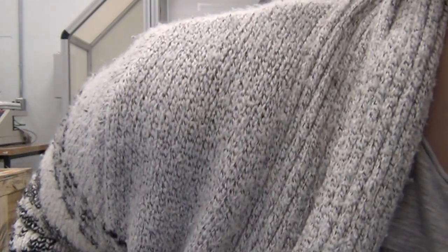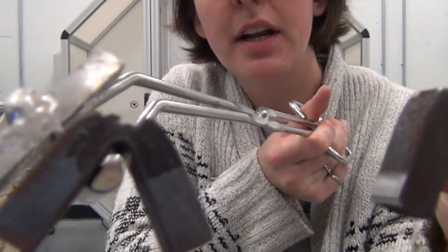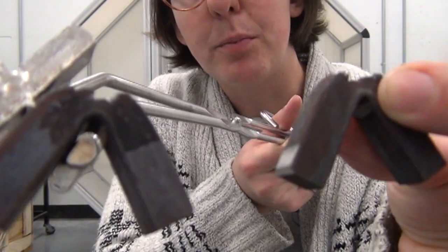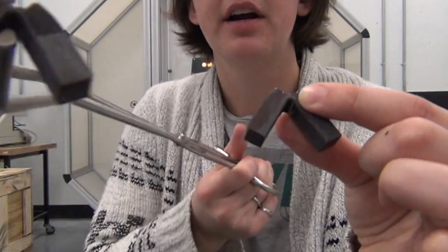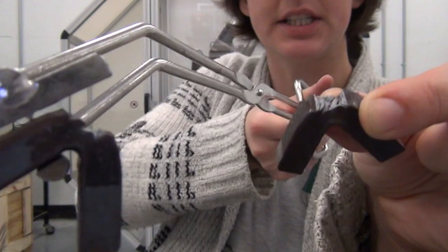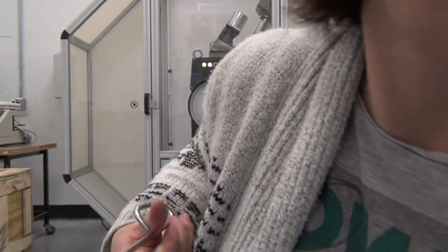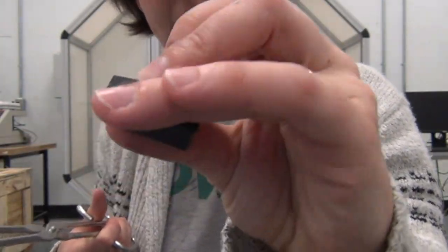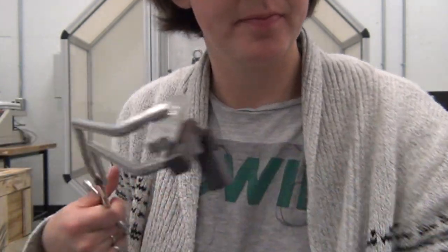And we can compare again between our room temperature sample and our boiling water sample in the tongs over here. We have pretty similar ductile fracture characteristics. And we have our brittle fracture over here at our minus 70 degree sample. So keeping all this in mind, we know that our ductile to brittle transition temperature for our steel samples must be somewhere between 23 degrees and minus 70. And by plotting our impact energy and temperature, we'll be able to find exactly where it is for the steel and also for our brass and copper samples.